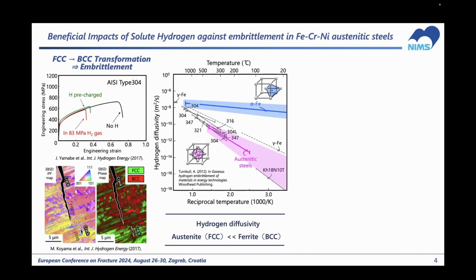But in other words, once the metastability of austenite triggers phase transformations from FCC to BCC martensite, as many people here know, embrittlement suddenly happens even in austenitic steels due to the cracking of the martensitic phase itself. So at least one primary requirement for the achievement of great hydrogen resistance in austenitic steels is to ensure the phase stability of austenite and completely suppress the occurrence of martensitic transformations. That is attained by the sufficient addition of alloying elements, including chromium and nickel.